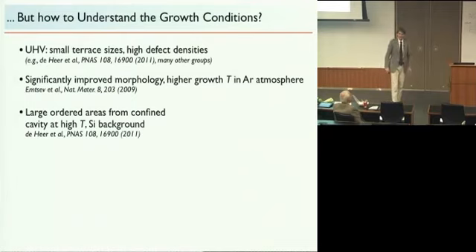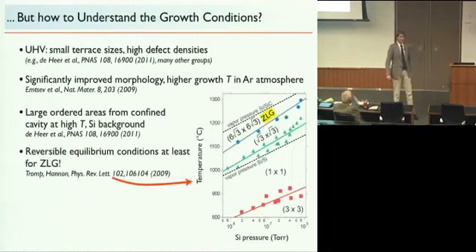And when temperature and pressure come into the game, it somehow sounds like thermodynamics. And in fact, there's a publication from an IBM group from 2009 that draws a temperature-pressure phase diagram for silicon carbide surfaces. What you see here is different surface structures that are stable at different temperature-pressure conditions. 3 by 3, 1 by 1, square root 3 by square root 3 are just labels of structures that are not yet graphitic. But importantly, this zero-layer graphene that I showed you before also has a stable temperature-pressure range.